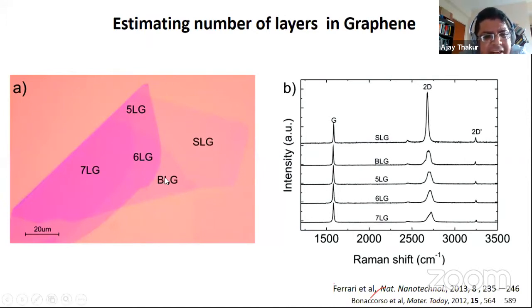this entire layering has been done on a silicon dioxide surface. So a thin silicon dioxide film is grown on top of silicon, and on top of the silicon dioxide layer, graphene has been transferred. And then one can see this SLG, which is essentially the single layer graphene region, where you can see a slight change in transparency. Then there is bilayer graphene, and then there are all kinds of 5 layer, 6 layer, 7 layer, and so on.